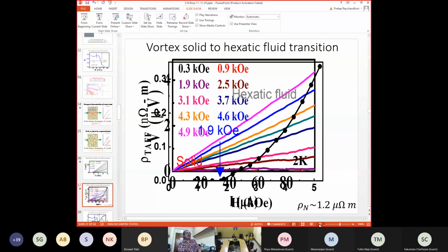At low fields, which is up to 1.9 kOe, there is no voltage that appears, so the resistance is 0. But after that, you have a small voltage that keeps appearing and then gradually increases. So if I plot the resistance from the slope of the IV curve, I see that around 1.9 kOe, I start seeing this finite dissipation appearing, and this is the transition from a solid to a hexatic fluid. Okay, now this is the first transition. What about the second transition?